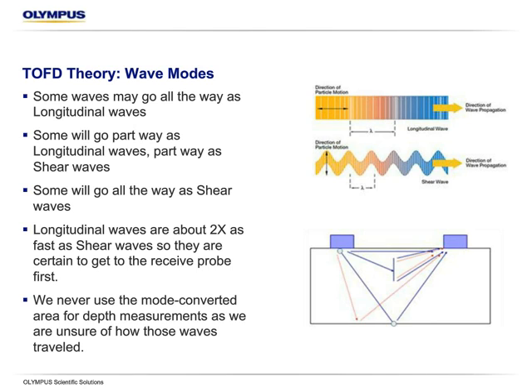So when we set up the display, which we'll see in the next few things, we always want to be aware of which zones we're using, where the signal might occur, and what may be the propagation mode. It makes it pretty easy because these two wave modes travel at distinct different velocities. The reason we use longitudinal waves as the main detection and sizing area for time of flight diffraction is because they are about twice as fast. So we know when they're going to occur, and they're going to occur first. Just be aware not to use the mode converted areas too much.